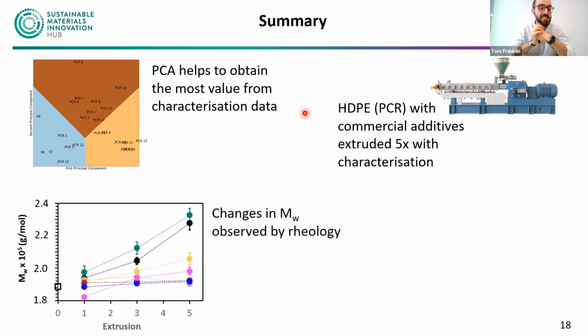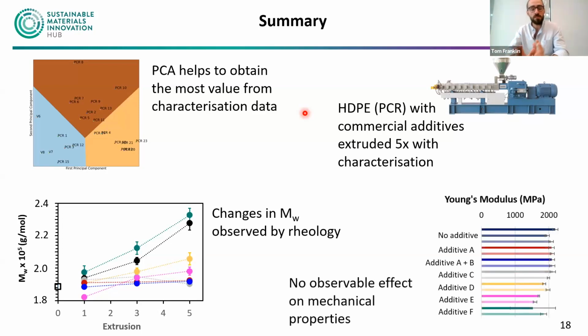Some of that data is molecular weight. From rheology, we do see changes in molecular weight, so we know that chemically structural changes are happening to our resins, but that by and large does not translate into mechanical properties. So this could be that polyethylene as a whole is quite resistant to degradation. Despite having changes in molecular weight, despite having changes to your base chemical structure, that doesn't really translate to mechanical properties. It will still perform fairly well in its intended application. In this case, plastic bottles.